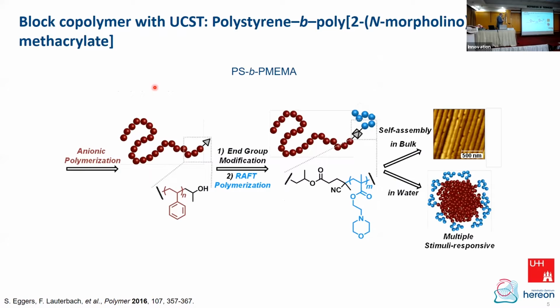Then the next point was that we wanted to have block polymers. So Stefan also knew that I'm a block polymer guy. So okay, let's do block polymers. And at that time, with RAFT polymerization, we were not so advanced. And styrene, which is here the red block, is not so easy to polymerize by RAFT polymerization when you want to go to high molecular weight. RAFT often has the disadvantage that it's difficult to achieve really high molecular weight, that means something in the range of 100 kilodalton. So that is difficult, or was difficult.